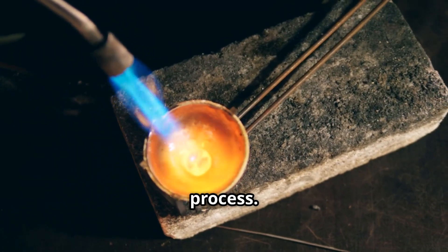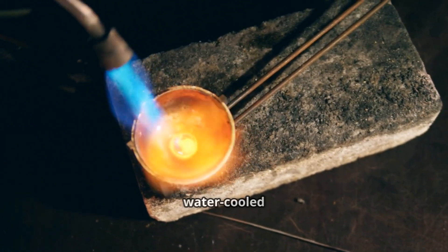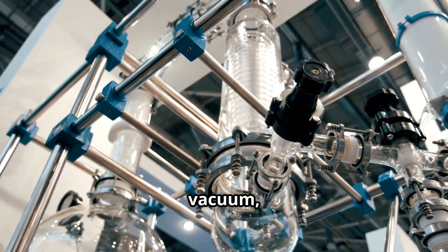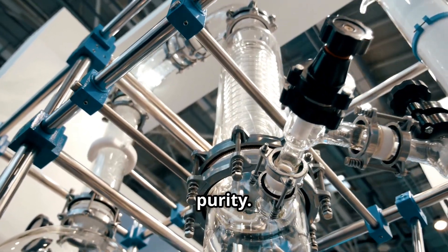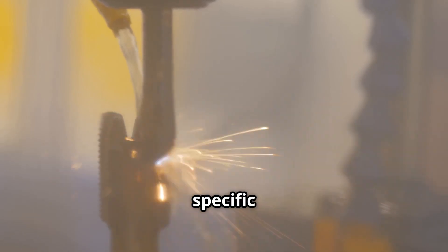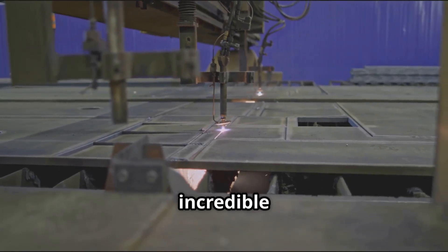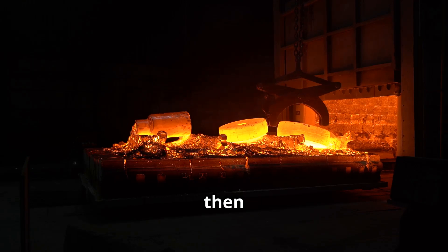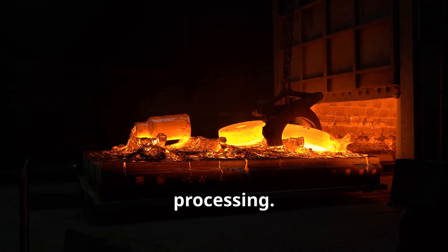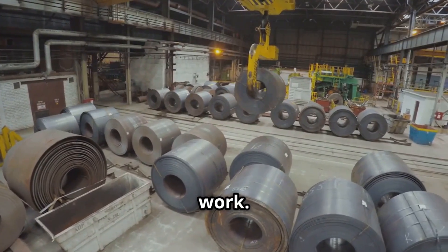VAR is a precise process — an electric arc melts a titanium electrode, dripping molten metal into a water-cooled crucible, all in a near-perfect vacuum ensuring atomic-level purity. Electron beam melting uses high-energy electrons to precisely bombard and melt specific areas of the sponge, like a computer-controlled welding torch with incredible precision. The molten titanium is then cast into massive ingots, with a single ingot weighing several tons and representing weeks of careful work.